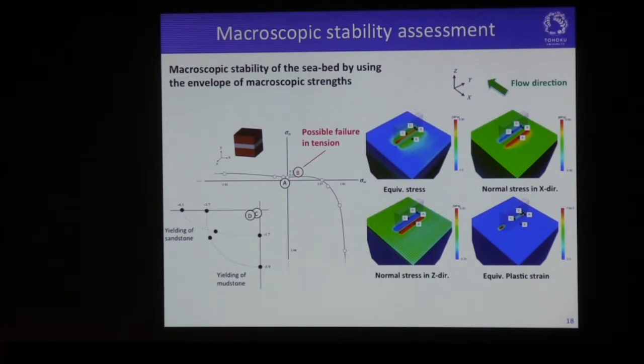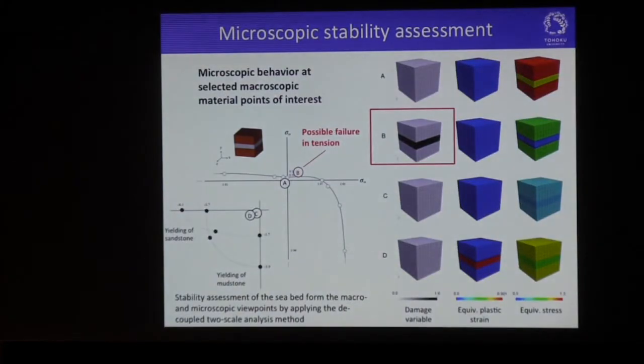At the same time, we can conduct localization analysis based on the homogenization theory, so we can extract the deformation history of these material points to the unit cell to have the microscopic mechanical behavior at the points of interest here. These are the microscopic mechanical behavior obtained by the localization analysis. Here, look at this. This is the point of possible failure in tension from the macroscopic viewpoint. Here is the microscopic response that suffers from the damage of the sandstone here. So we can assess the strength and stability of the seabed from the macro and the microscopic viewpoint by applying the decoupled two-scale analysis method as well.